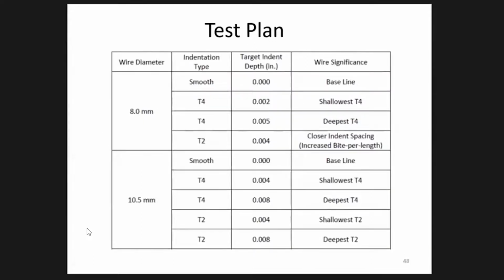At the time of the original study, essentially all the plants were using 5.32 millimeter wires. Since then, Nortrack has used 8 millimeter wires and Rail One used 10.5 millimeter wires. So these various diameters are really being used worldwide. We looked at 8 millimeter wires and 10.5 millimeter wires. For the 8 millimeter wires, we had a smooth as a control. The T4 is the indent that tapers to shallow out at the edges. The T2 is deep all the way across. We targeted indent depths of 0.002 of an inch all the way up to 0.005 of an inch. For the 10.5 millimeter, we looked again at a smooth, 2 T4s, a shallow one at a depth of 0.004 and a deeper one at 0.008, and 2 of the T2 style indents.